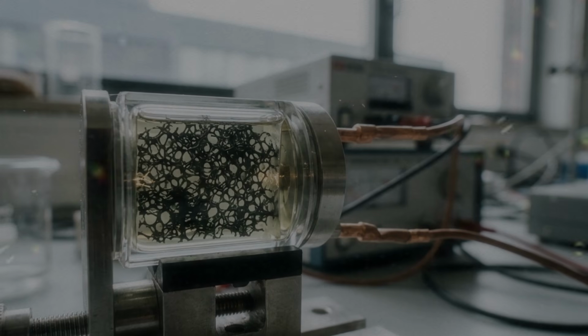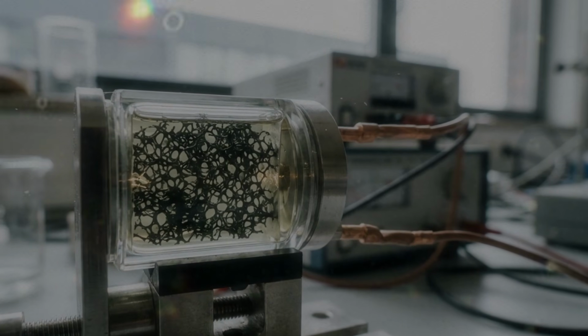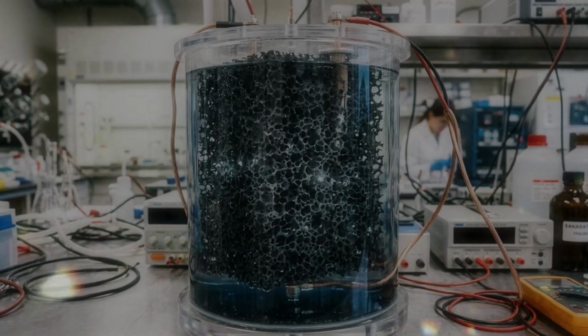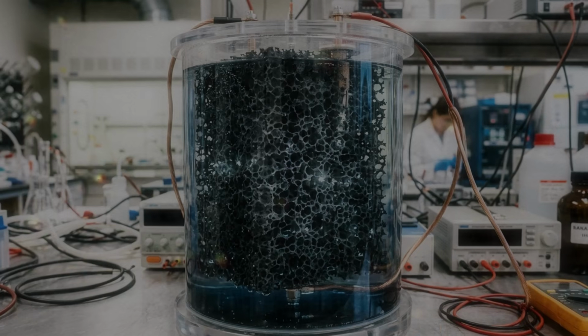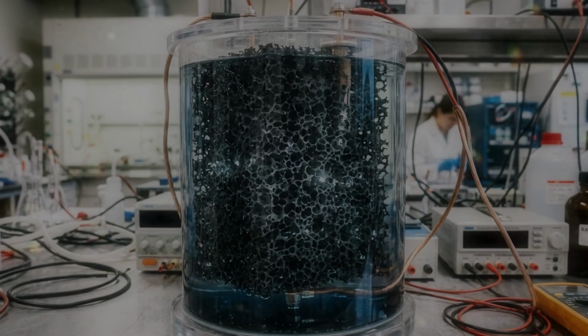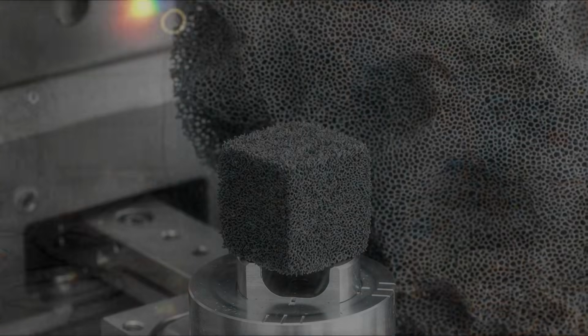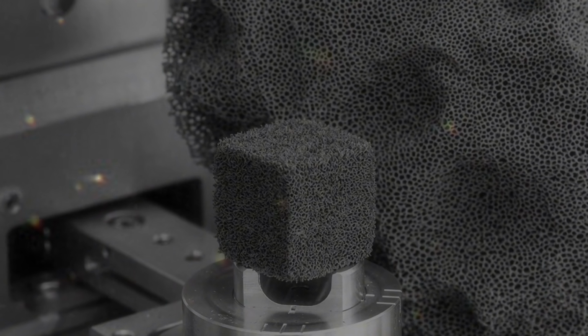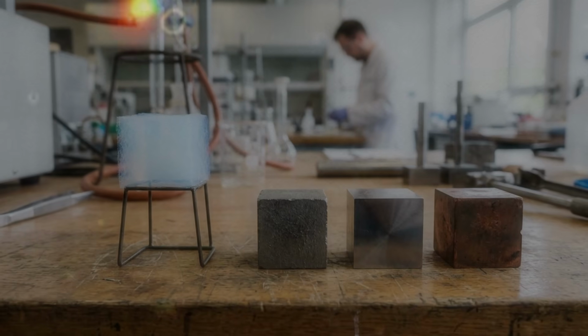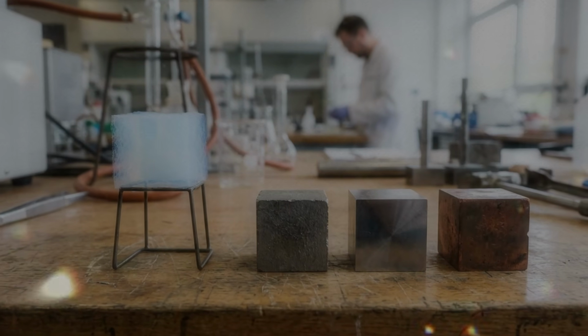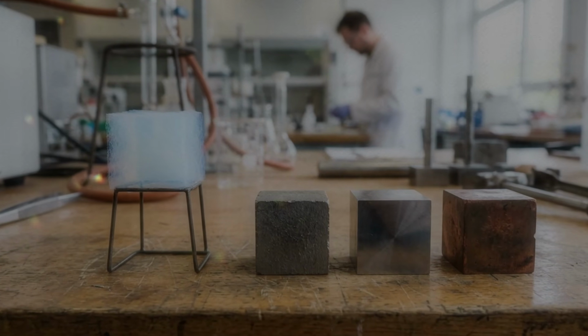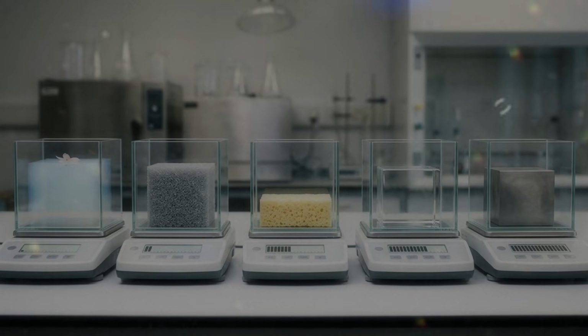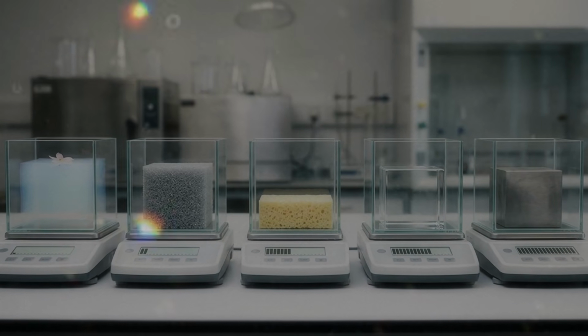Mechanical behavior adds another group of unusual effects. Some aerogels are rigid and brittle, others are flexible and springy. The difference comes from the material in the framework and from the way the pores collapse. Silica aerogel often resists small forces without much movement, then cracks once the stress becomes too large. Graphene aerogel can bend because its walls are thin sheets. The sheets wrinkle, fold and slide before the carbon bonds themselves break.